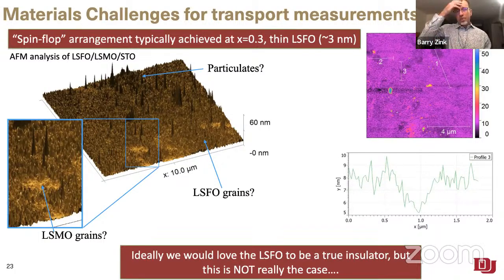One thing that we found out relatively quickly is that the arrangement that had previously been well understood to give this kind of spin flop coupling, this rigid coupling of the Néel and the magnetization vectors, had this very thin LSFO layer. You can just do some AFM. You see all of the real complications of real materials. In this particular case, it involved some sorts of particulates and things that you often see for pulsed laser deposition grown materials. Not always, but they're often in there. You also see just basically missing grains where the LSFO has popped off, and you can see the LSMO just underneath.